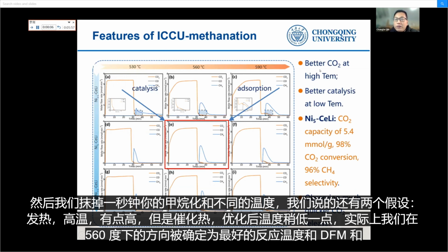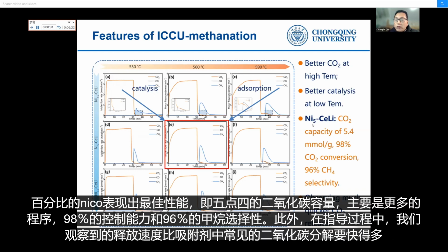We saw that CO2 adsorption favors a little higher temperature, but catalysis favors a lower temperature. After optimization, 560 degrees is determined to be the best reaction temperature, and the DFM with 5% nickel shows the best performance, with a CO2 capacity of 5.4 millimole per gram, 98% CO2 conversion, and 96% methane selectivity.